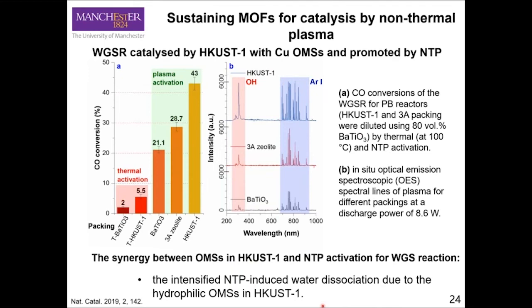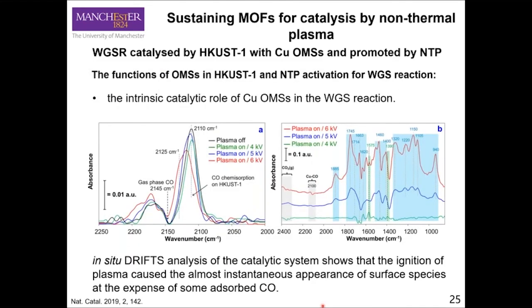But most important, this work is actually about, we try to prove this is surface reaction, because catalysis has to be surface reactions. If we have the MOFs packed into the non-thermal plasma system and basically enhance the plasma discharge, and therefore enhance the gas phase conversion of CO and water to hydrogen and CO2, then this is not catalysis. Because what we want is the copper metal site in the Morph to do the work.